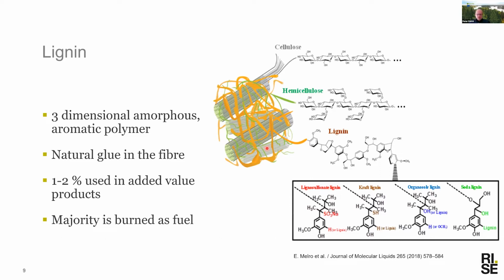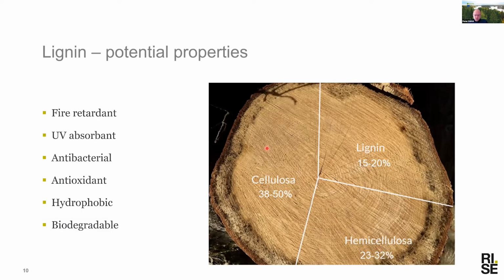Now, if we look at lignin, which is one of the candidates here for a water barrier, we have a three-dimensional amorphous polymer phase. Today, we're using about 1 to 2% in added-value products. If we could use this in the barrier, this would increase quite considerably. The majority today is burned as fuel in one way or another, or added in fuel. And that's a shame, because lignin has quite a lot of great potential.